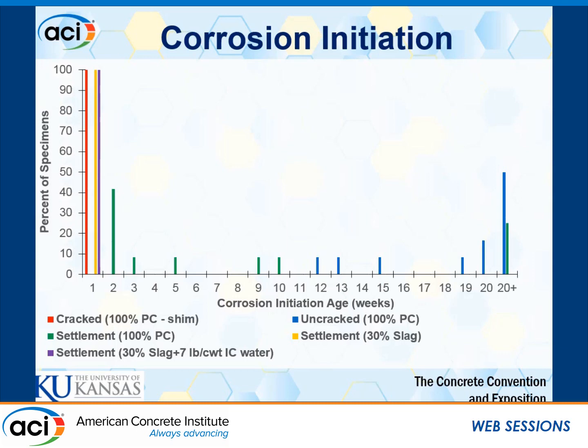Moving right along, when we looked at our settlement cracking specimens with 100% Portland cement, we had to wait till about week 2, and then we only saw about 42% or so of those initiate corrosion. And then we kind of start trickling off there until we get into 12 weeks, which tends to be the earliest time for our uncracked specimens to initiate corrosion. And then some of those can take as much as 20 weeks or even longer. And it's important to note that even though some of those settlement cracking specimens at 100% Portland cement had cracks, not all of those initiated even at 20 weeks.